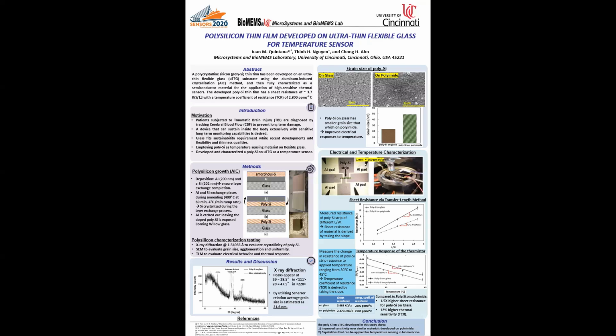Then, by using a scanning electron microscope, we look at the grain sizes and agglomeration of the grains. By comparing it to previously developed polysilicon and polyimide, it's clear glass has a smaller and more agglomerate grain. This suggests higher thermal responses from the glass substrate developed material, as the last test will confirm.